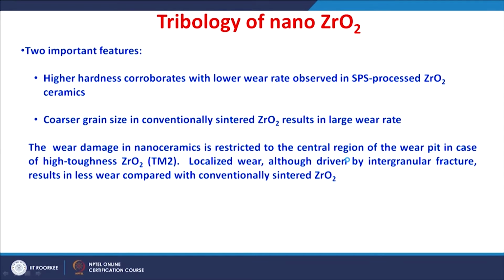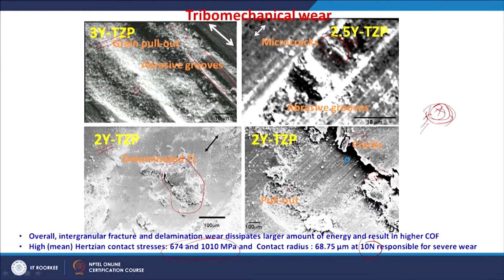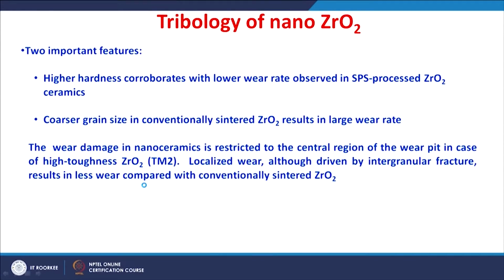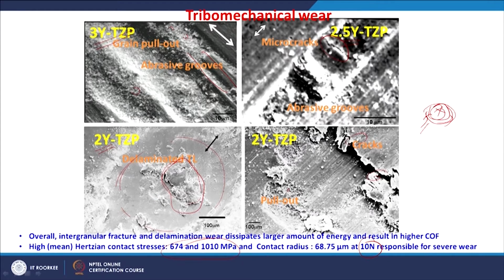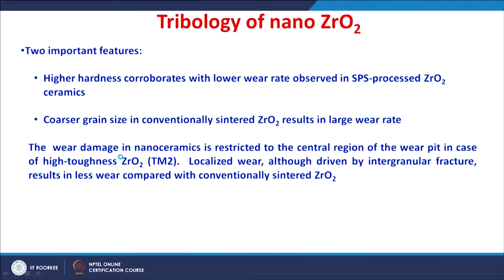So, the wear damage in the nanoceramics is restricted to the central region, as we have seen here, whereas the other region in the contact is more or less a smoother region. So, the wear is actually confined to the central region of the wear pit in case of the ceramics, particularly those with the higher toughness. Among the investigated ceramics, the 2 mole% yttria stabilized zirconia showed a maximum toughness. Because of the higher toughness, the wear damage is restricted only to the contact stress region, which is maximum at the central region of the wear pit. So, it is localized wear. Such a localized wear, although driven by intergranular fracture, results in lesser wear compared with that of the conventionally sintered zirconia.